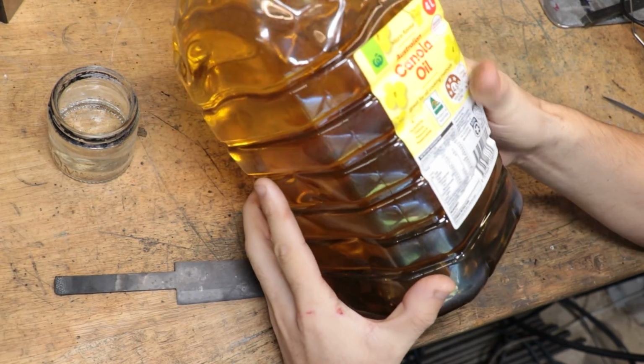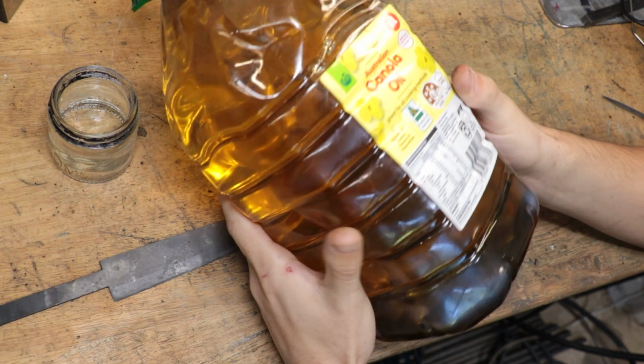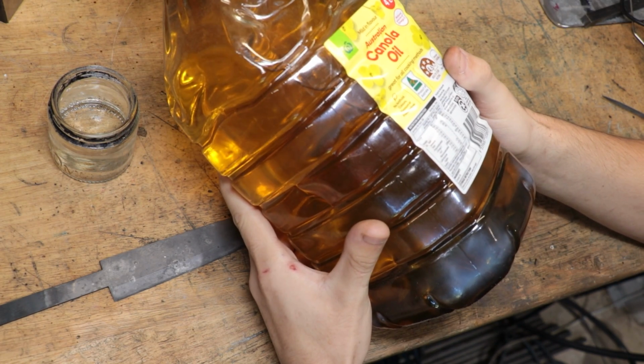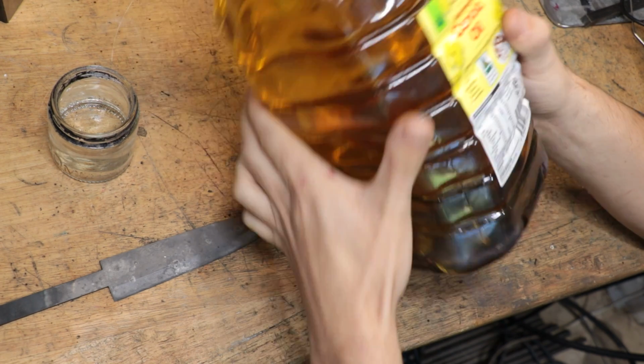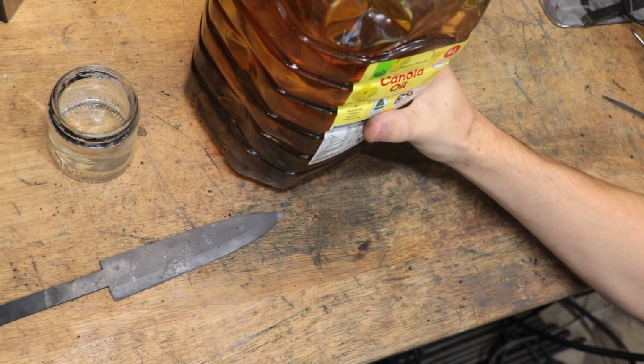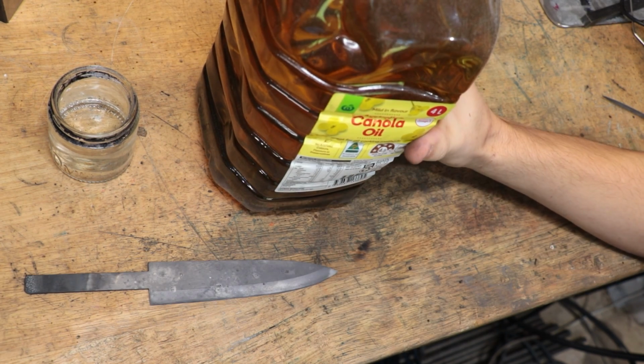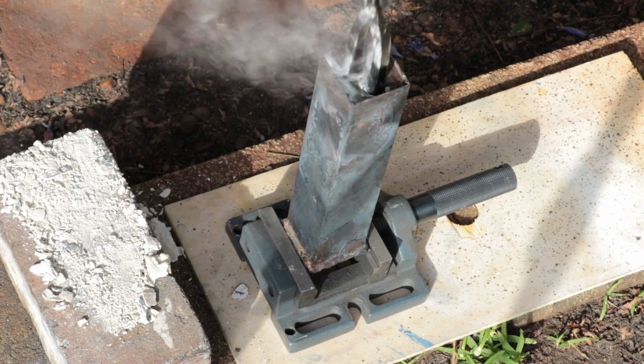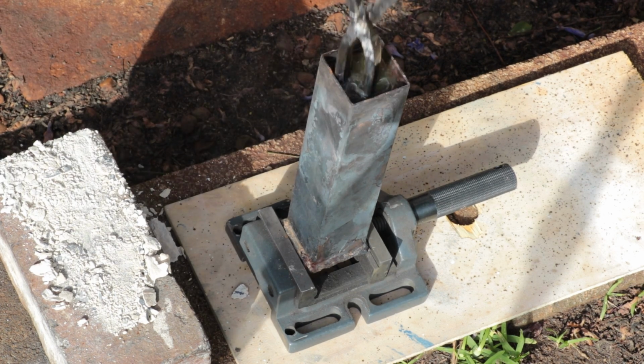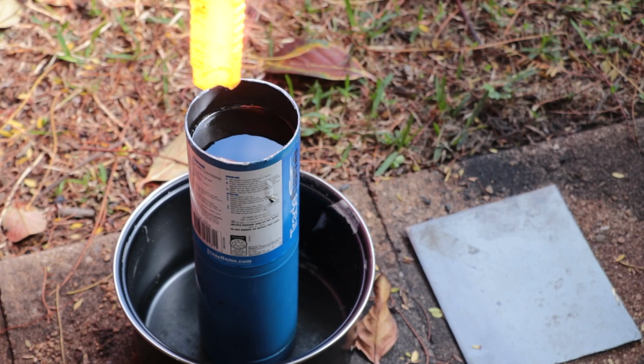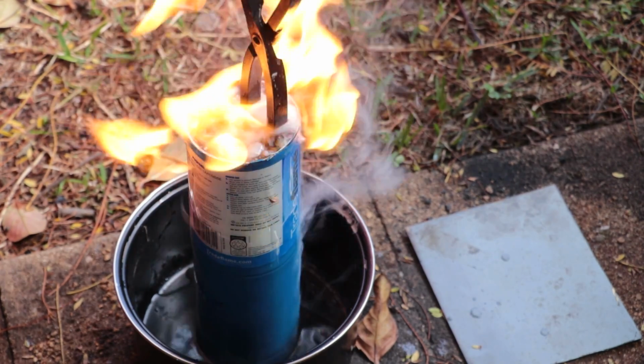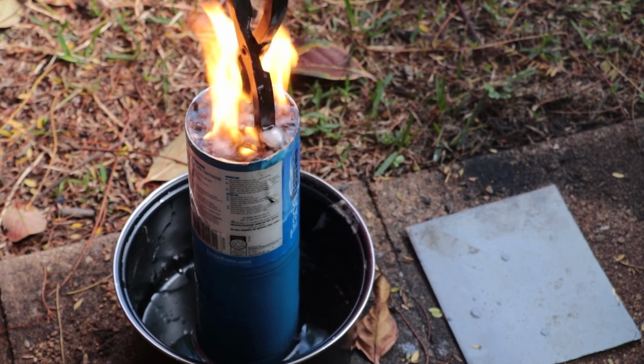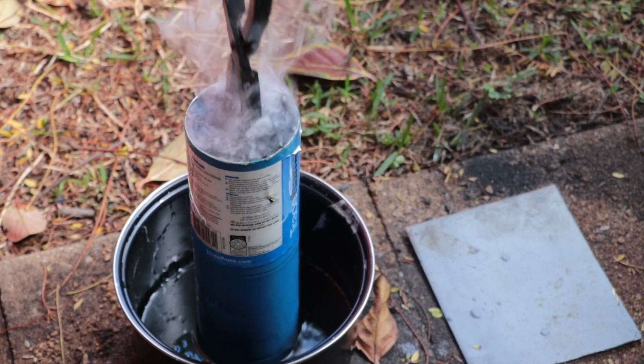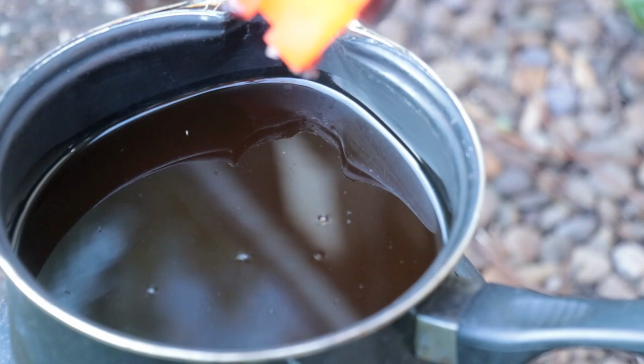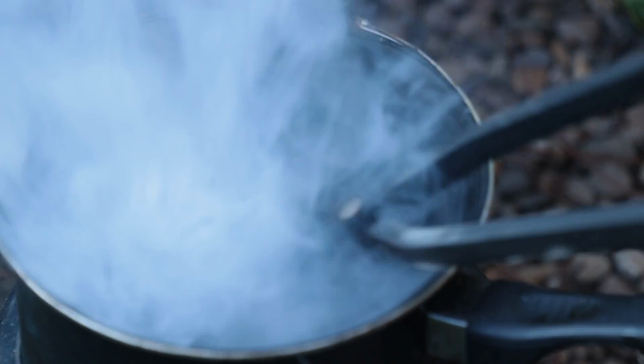On the other hand though, oil cools at about 1/3 the rate of water, so the risk of distortion and cracking is far less. But generally with carbon steel, it will tend to result in a part that isn't as hard, although it seems to be very dependent on the mass of the part that I'm quenching. Smaller parts tend to come out closer to 60-65 Rockwell C hardness, which is very close to water, but as the part gets bigger, it tends to drop into the 50s. I've also played around with using hot oil or small volumes of oil to reduce the rate of cooling to help reduce the potential for warping, and that seems to work well, but it does leave the hardness in the high 40s to low 50s Rockwell C hardness.